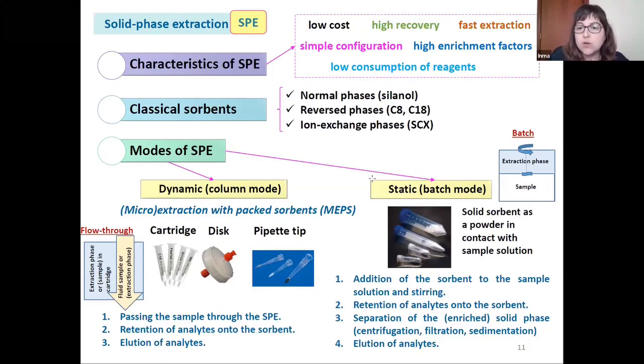In static mode, also named batch mode, the solid sorbent is usually a powder that is in contact with the sample solution. During the stirring, the retention of the analyte into the sorbent is produced. Once the retention is performed, we need to make a separation of the solid sorbent enriched with the analytes from the aqueous sample. So typically centrifugation, filtration, and sedimentation can be performed for this phase separation. Additionally to the phase separation, elution of analytes has to be done by the corresponding eluent.